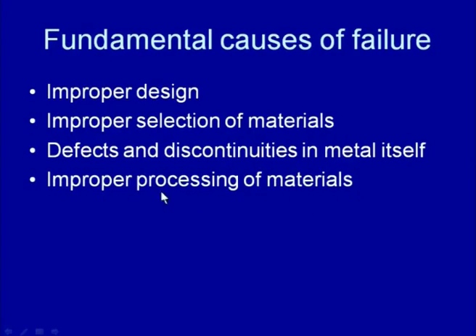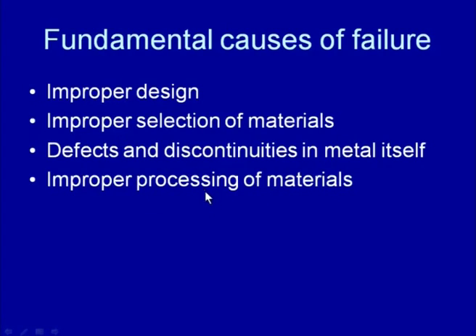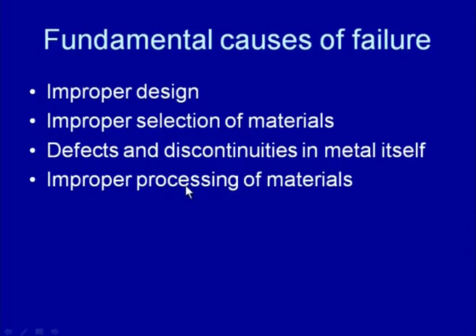Improper processing of the material means the recommended processing parameters are either not proper or not being exactly followed. For example, if a particular steel is supposed to be heat treated at 800 degree centigrade, followed by rapid quenching and then tempering at 300 degree centigrade, but neither the temperature nor the recommended time values for the heat treatment are followed, then that can lead to either excessive hardening or softening of the material. This can lead to properties which are not expected in the particular engineering component. So, lack of proper processing parameters can lead to a number of undesirable features, which can be the source of failure.